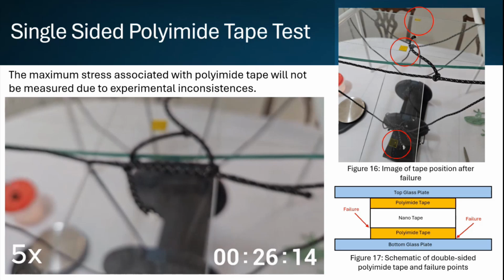But we can see that there was a failure. You can see in figure 16, there was a failure between the polyimide tape and the nanotape and the polyimide tape and the bottom glass plate. I didn't want that. I needed to be able to see a clear indication that the polyimide tape couldn't adhere to the glass plate, not the nanotape adhering to the polyimide tape, because at that point I was just measuring the adherence between nanotape and polyimide tape. For this reason, I'm not going to report my findings from this due to experimental inconsistencies.